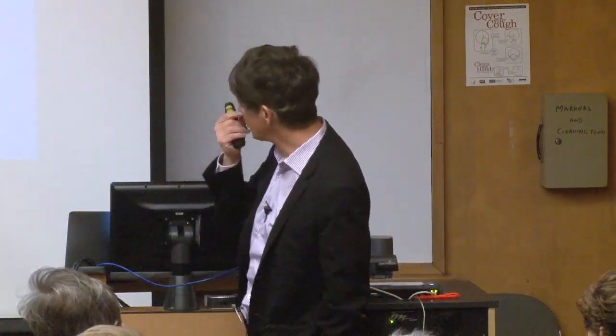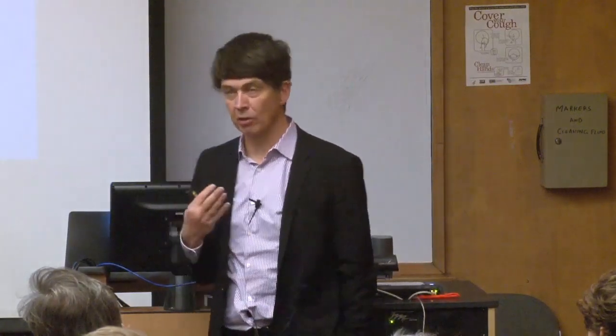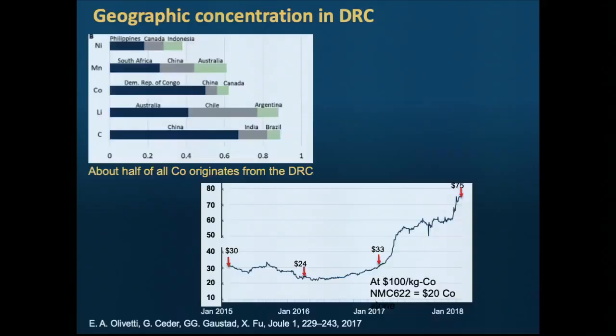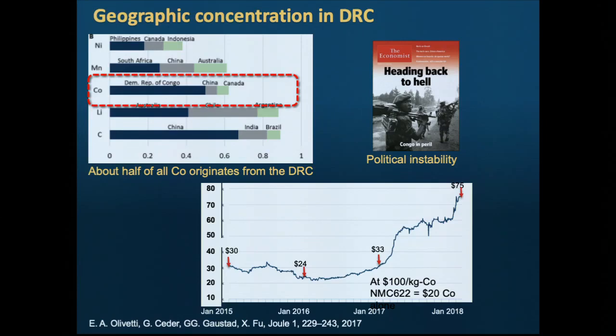The other issue in terms of resources is that when you think of criticality of resources, you think a lot about geography. And what this shows is which fraction is located in a single country. And for cobalt, it's one of the worst elements ever. More than 50% comes out of the Democratic Republic of Congo. And democratic is a misnomer here, right? If you know how the regime in Congo worked. As I always say, Congo is only one dictator away from even more chaos. But that's actually where 50% of our cobalt comes from.